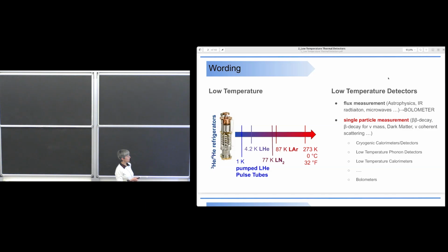Here you can see how we can achieve different temperatures below room temperature, and the technologies are that we use cryogenic liquids when we want to cool down something at, say, 100 Kelvin, for example. We can use either liquid nitrogen or liquid argon, as it is done for LEGEND diodes. If we want to achieve even lower temperature, we can use liquid helium at 4.2 Kelvin.